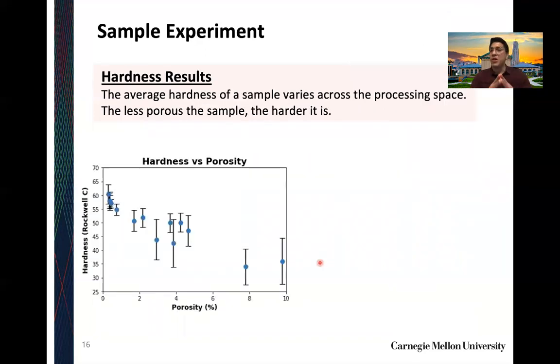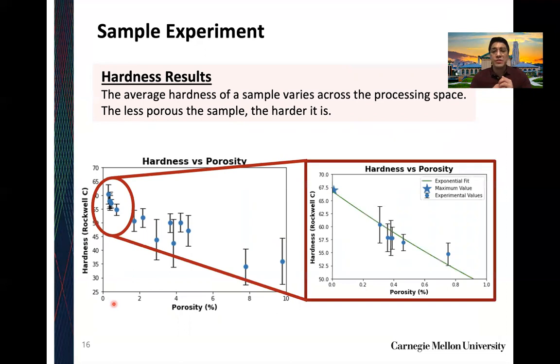And just to show the hardness results, as you can see here very clearly, as our porosity increases, the hardness also decreases. That's expected, right? Porosity acts as stress concentrators, which further increase the indenter's ability to indent into the part. And if we zoom in here, we start to see that at very low porosities, we